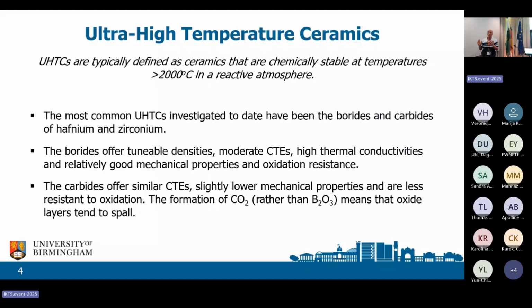The most common UHTCs investigated to date have been the borides and the carbides of hafnium and zirconium. You will see why shortly. The borides offer a number of advantages: tunable densities, moderate CTEs, very good thermal conductivities. That is really useful, because with very high temperatures you want to get the heat out of the system as quickly as you can. Of course, you always want good mechanical properties. As I say, they are non-oxides, and most of those applications will have oxygen present, so you need oxidation resistance.